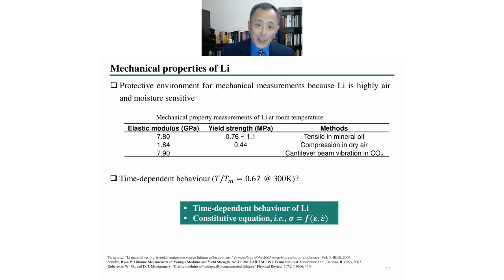Again, the measurement of a mechanical property is non-trivial because lithium is highly reactive. It can react with oxygen and nitrogen and moisture in air. So measurement can be challenging, and there are only a few reported values in the literature. And the Young's modulus values reported previously do not agree. Furthermore, room temperature is a relatively high temperature for lithium, since lithium melts at 180 Celsius. So the ratio of room temperature to the melting temperature of lithium is quite high, 0.67 at room temperature. One can therefore expect time-dependent deformation behavior for lithium.